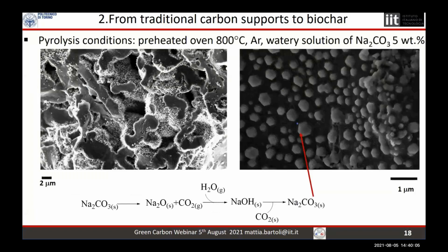It is a very, very interesting structure with a very high surface area in the range of 400 square meters per gram, with a fractal structure made by collapsed spheres that is resembling the figure here, with hexagonal particles of sodium carbonate tightly bound on the surface. And this is very, very promising for all the applications that require a high surface area and a basic catalyst that is slightly less studied than acidic ones like zeolites, let's say in this way.